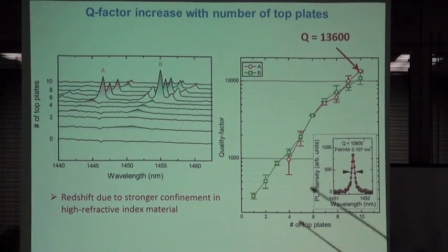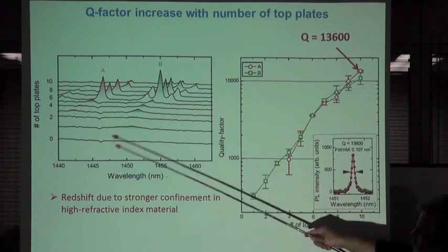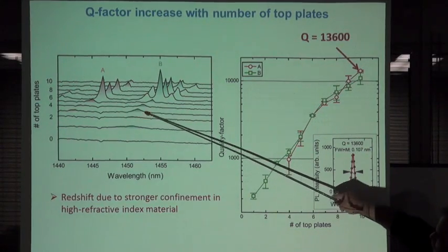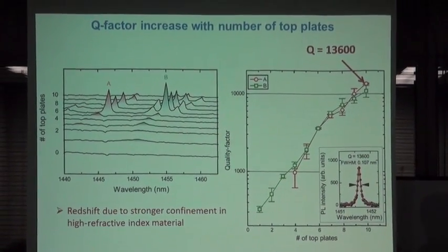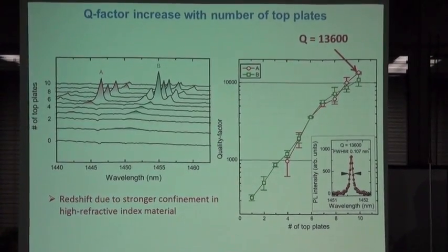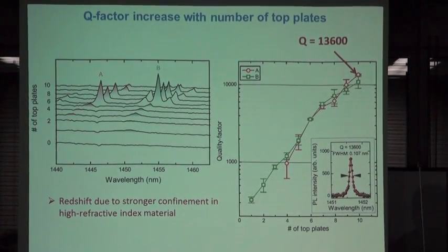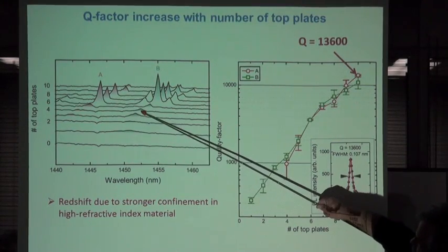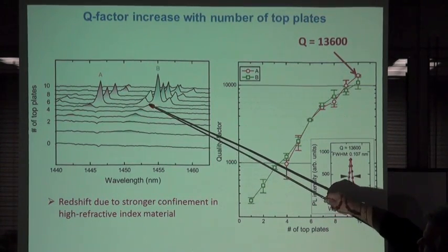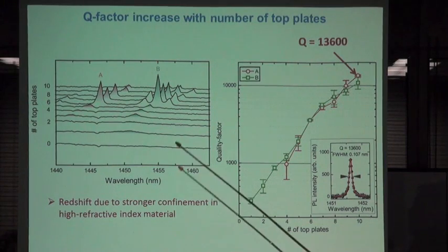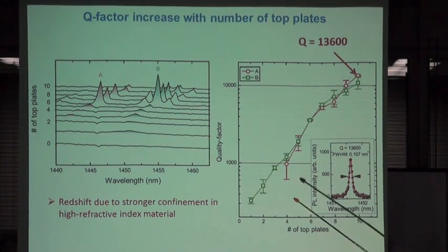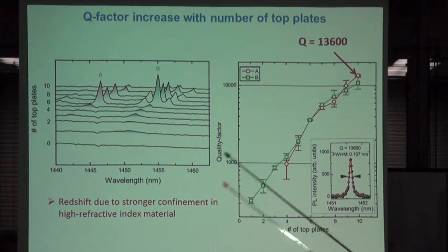Actually, if you look at the Q factor in this 3-dimensional photonic crystal, this is a semi-logarithmic scale here. So the mode is coming up, and also what you learn in classes that you need at least 1 unit cell to start. This is exactly what we have. We need here something like 4, 5 top layers. This is the number of top plates, and then we measure. So when we have no top plate, we don't measure any mode.